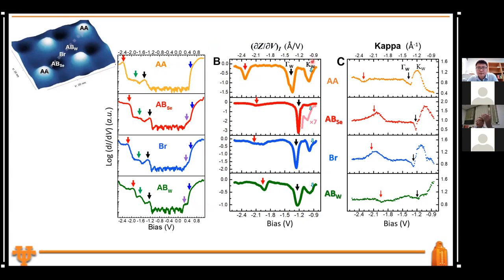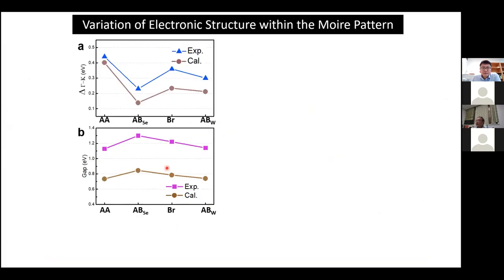So in the MoS2, WSe2 is a type 2 band alignment, and most of the valence band states are coming from WSe2. Then you see this separation change quite a lot from AA to AB site to bridge site to ABW site. And let's now look at, this is the experimental result. This is what we see. And theoretically, this is what you see, the separation between gamma and K.